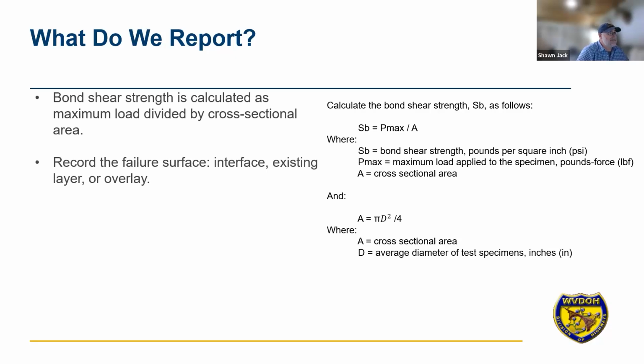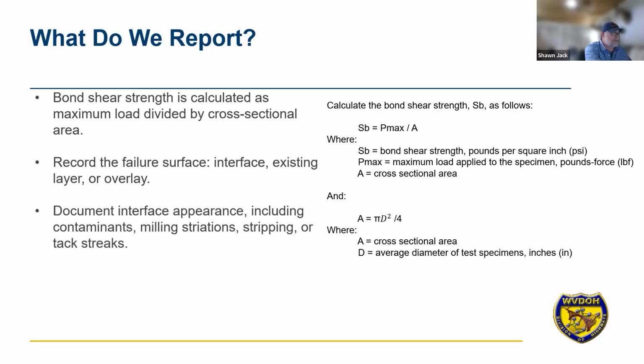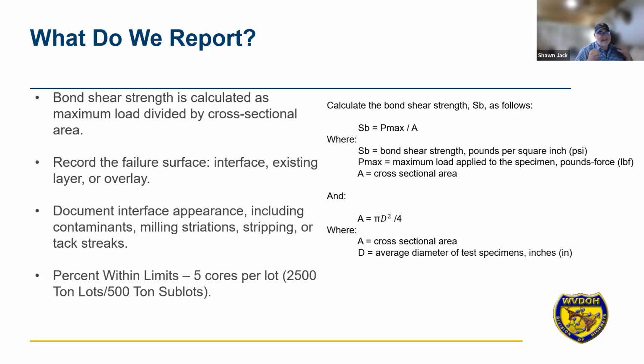So we want to record the failure surface, whether that's the interface, the existing layer, or the overlay. We want to document the interface appearance. That might be if there are any contaminants, striations, stripping, any kind of tack streaks, anything that you see that might be of importance later on if there's ever a question or a problem.